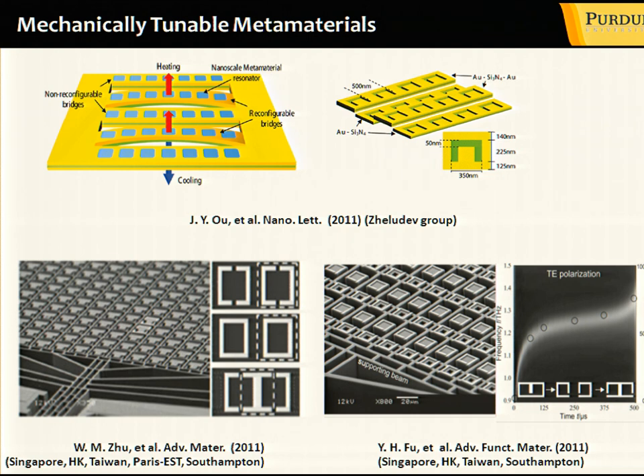If you use materials with very different thermal expansion coefficients, in this case, silicon nitride and gold, when you heat it up, of course, the structure would bend. And when the structure bends, you slightly change the sizes of your metamaterial elements, and therefore you shift the frequency, as it's shown here. But that was the first demonstration, and from that point, it was clear that you could make structures similar to MEMS or NEMS for metamaterial applications.